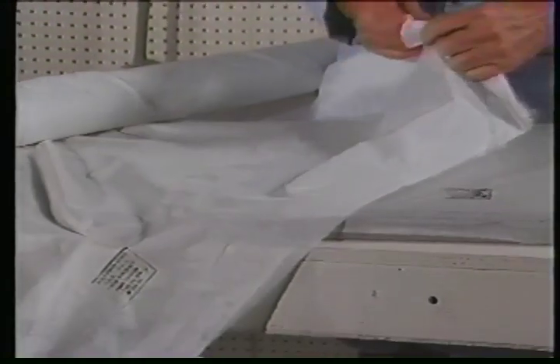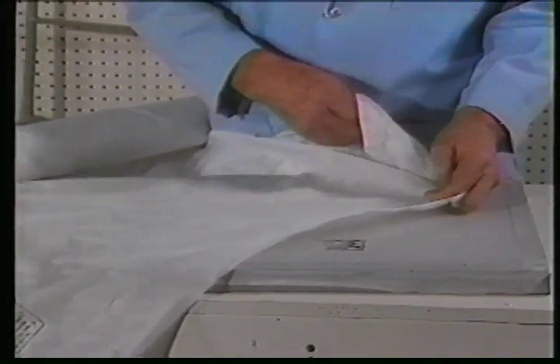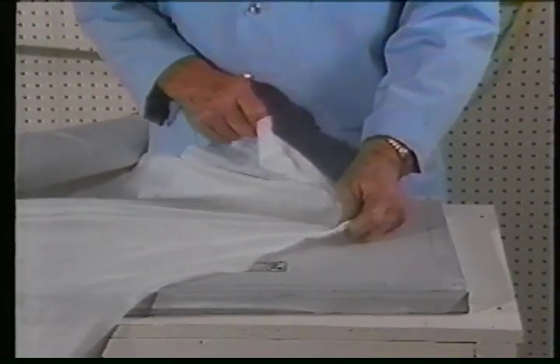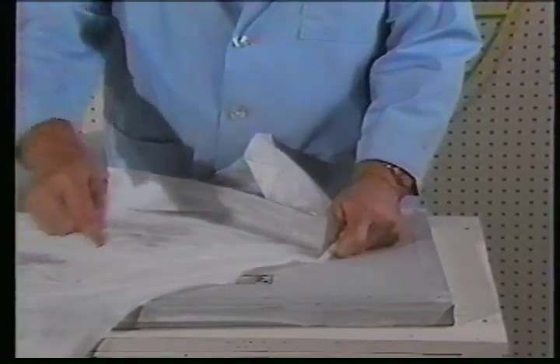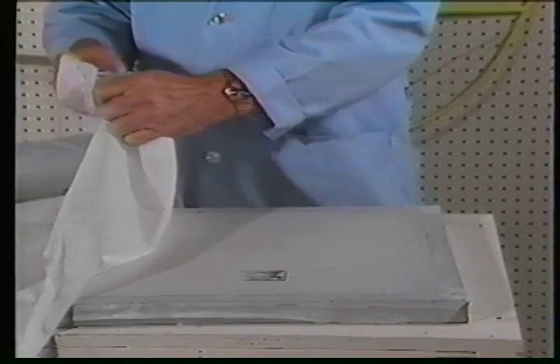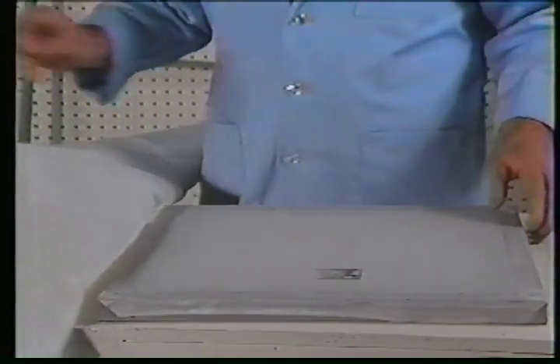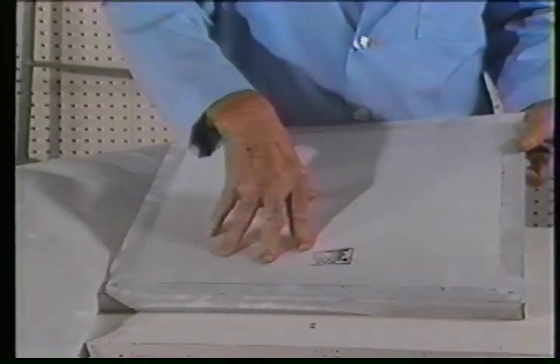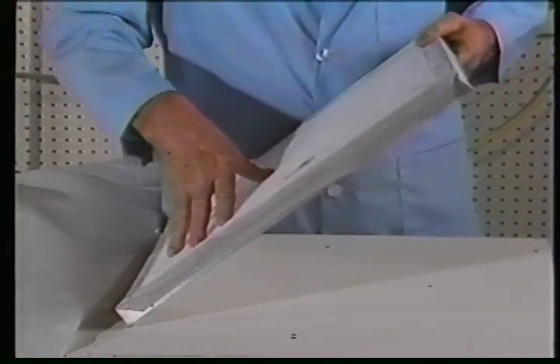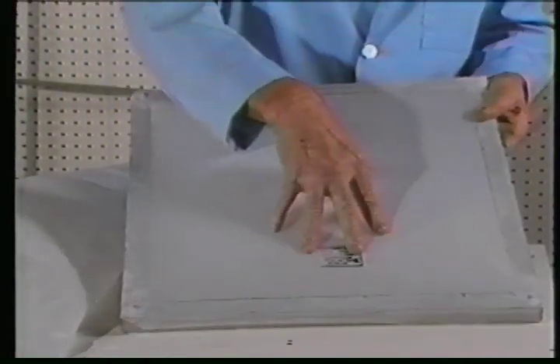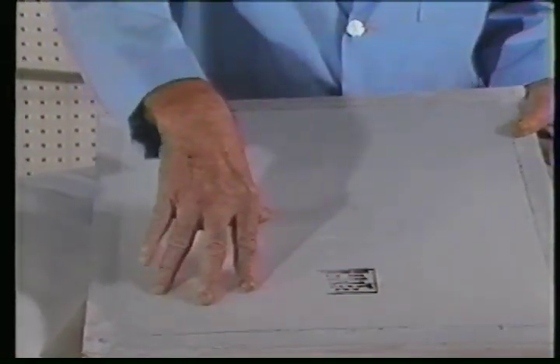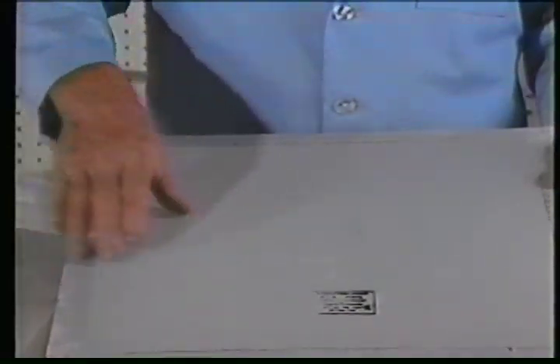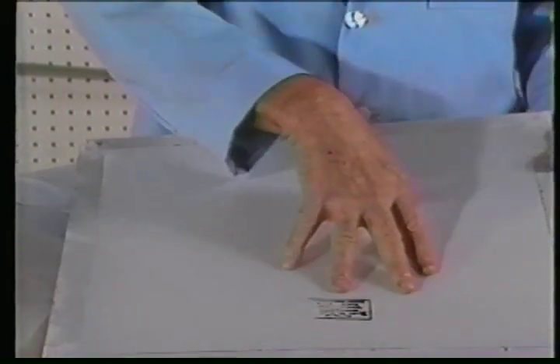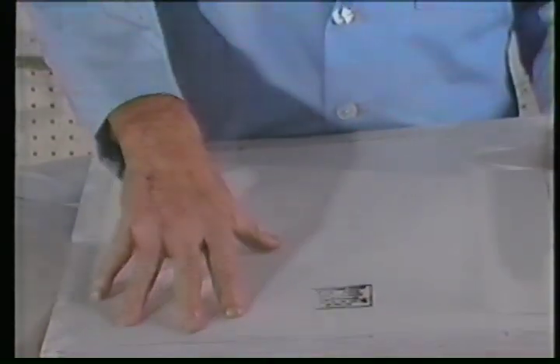Polyfiber fabric is custom woven from select polyester filaments to a specified thread count equal in warp and fill. When properly installed and a controlled temperature of 350 degrees Fahrenheit is applied, the tension developed will be between 1 3/4 and 2.5 pounds per inch, depending on the fabric style. It will never increase with age or heat from the sun and will not decrease in cold weather. Unlike metals, polyester fabric tends to expand at low temperatures.